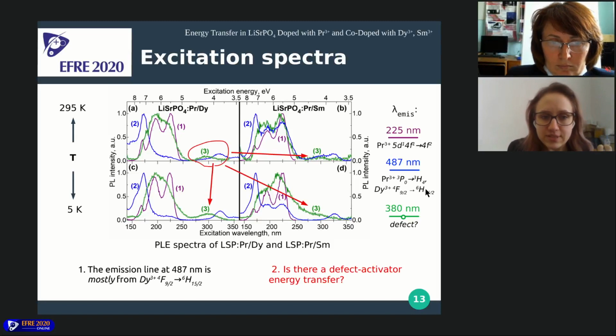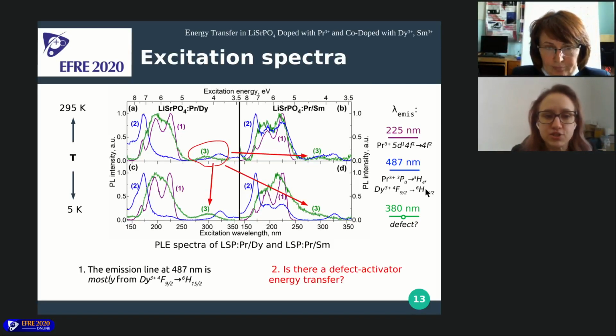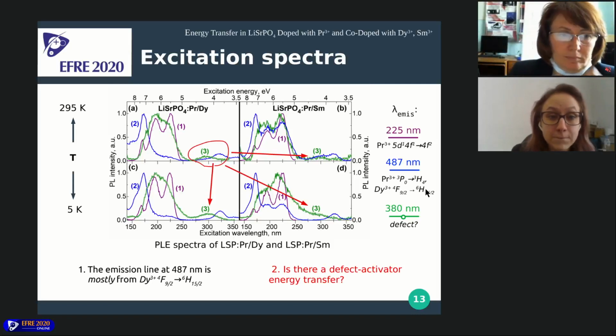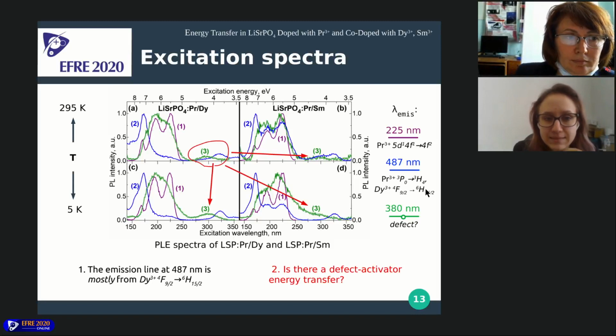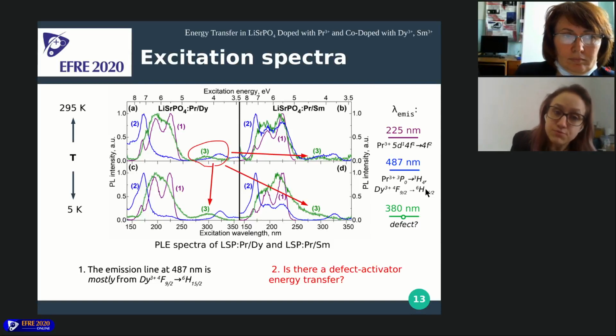The second point is the green lines in the spectra. It was measured for this presumable defect, and it has a band in the region of 300 nanometers, which cannot be assigned to any excitation transitions in these codopant ions. And also, you can see that the blue lines, which, as I said earlier, stand for praseodymium f-f emission, also can be excited in this region.